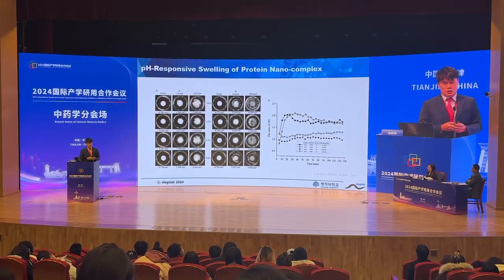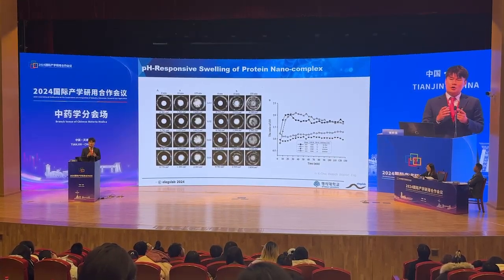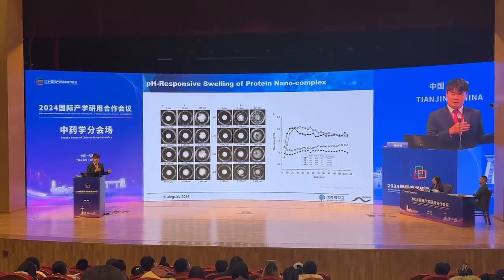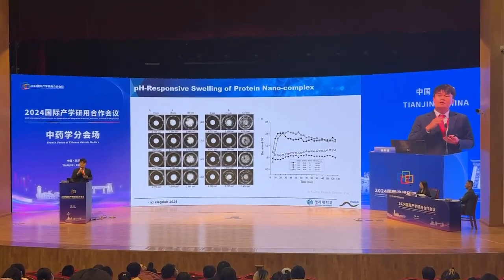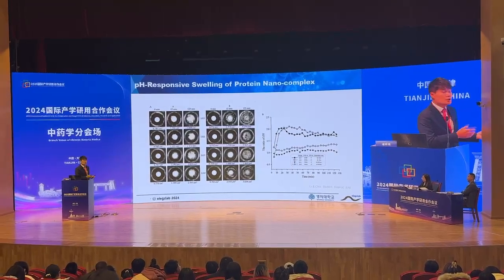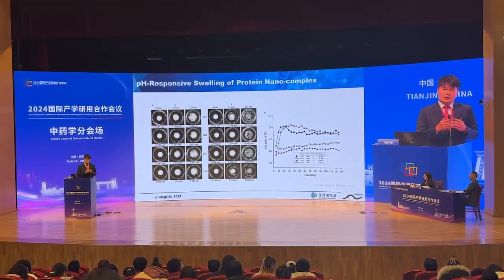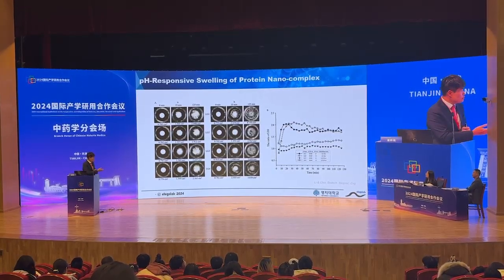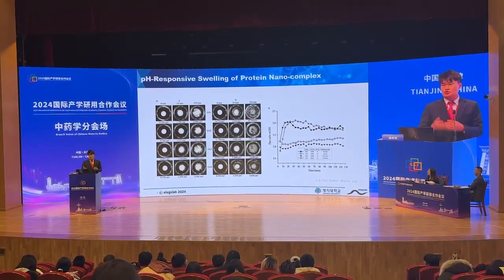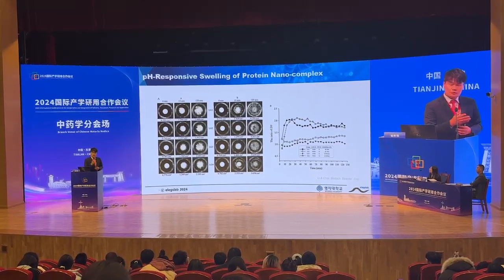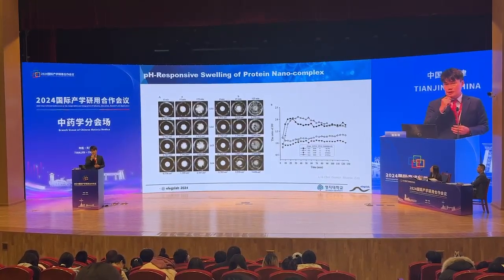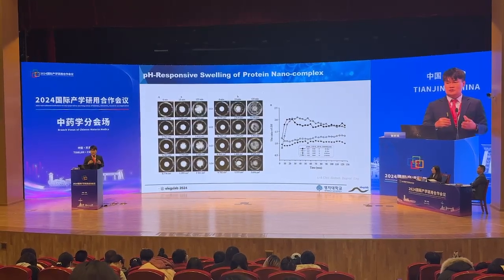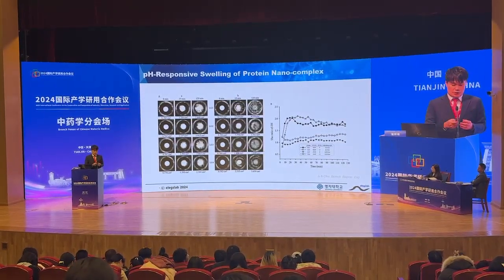We are making a tablet form of this oral vaccine. In the microscopic view, this tablet vaccine is pH-responsive. When in acid conditions, the tablet does not break down, but it does break down in neutral conditions. So when you take this tablet, it can be safely and stably delivered into the intestine.